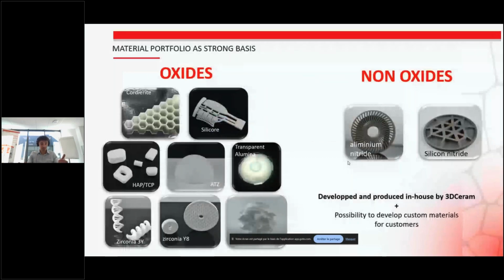About the standard mixes developed by the company, just for your information, we developed more than 15 mixes of materials possible to print with our SLA printers. Mainly oxides, such as alumina, zirconia, HAP and TCP, hydroxyapatite and tricalcium phosphate for implants, cordierite for space application, and others. And we also developed some slurries for nitrides, such as silicon nitride and aluminum nitride, mainly used for defense and space application as well.